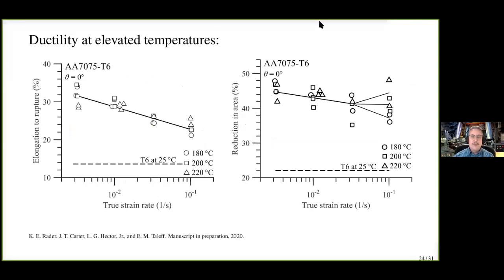So at these warm temperatures, we are certainly getting much better ductilities. So our elongation to rupture is plotted here for 3 temperatures, and I'm showing this as a function of the logarithm of strain rate. Here is our T6 ductility at 25 degrees Celsius, at room temperature. What you see is a significant improvement in tensile elongation to rupture. So we have much better performance for forming at this set of warm temperatures. We also have some strain rate sensitivity. So we now can see that the flow behavior is sensitive to the strain rate.